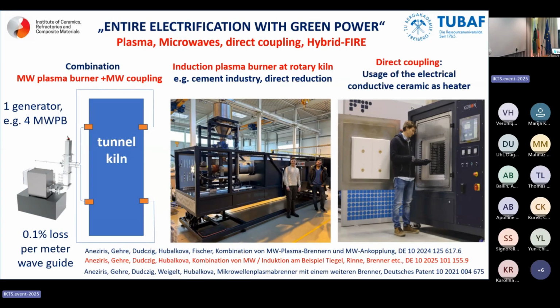We are also going to start in November this year with an induction plasma burner, a rotary kiln with induction plasma burner. Somebody would say, why? A lot of the processing routes, cement industry, not only, are dealing. And of course, if you have carbon bonded systems, which have not to be pyrolyzed, or also silicon carbide based systems and other issues, you can put also electrodes and you use them as a heating element during the pyrolysis. So you apply directly the energy where you want. Perhaps you could create also special structures.